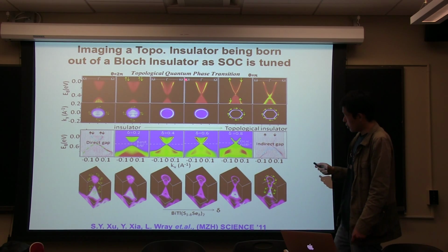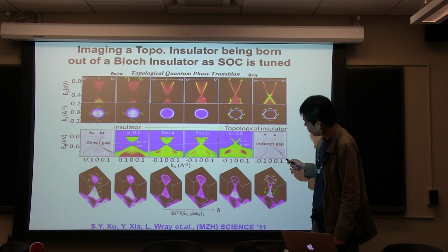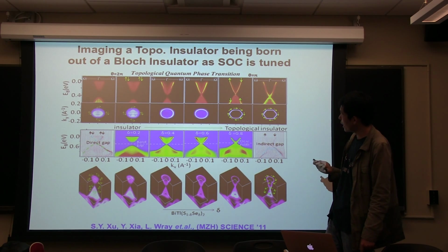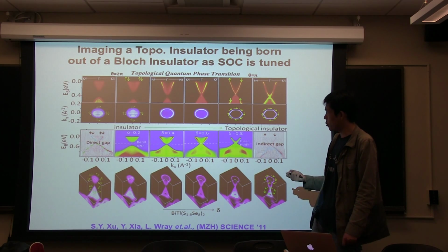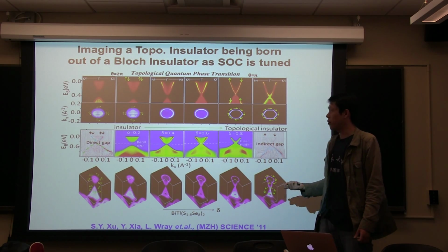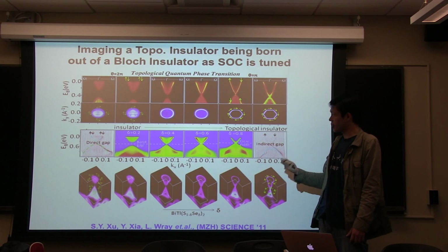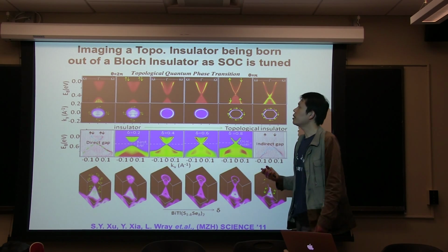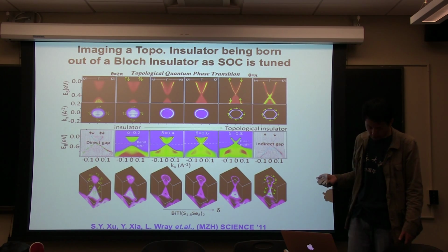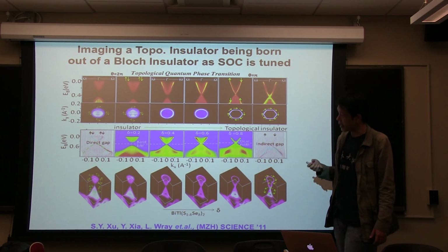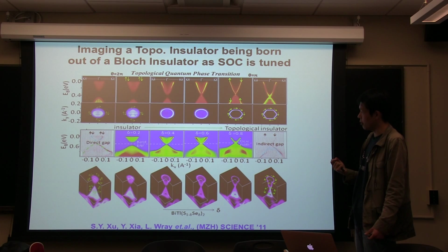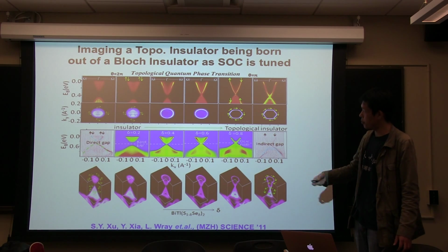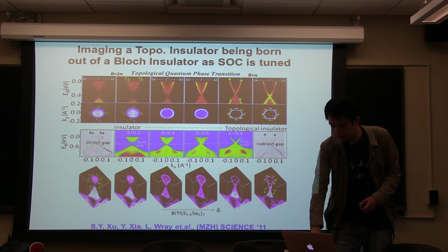Okay, so now if we take this critical composition and this Dirac semimetal, and then break the inversion symmetry or the time reversal symmetry of this thallium bismuth system, then we will get a Weyl semimetal state. But at that time we found out that for this particular system, breaking either symmetry is experimentally very hard. But this at least demonstrates the spirit or the methodology.